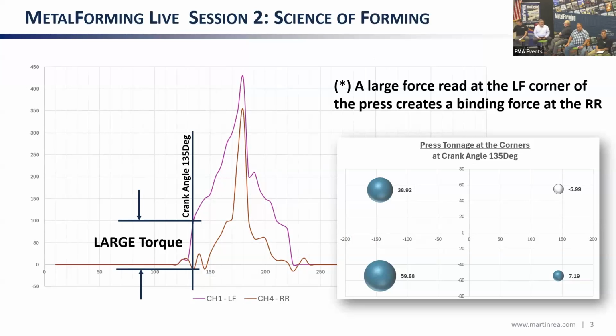Because of the signal we're getting from the right rear, we know that the press is sticking. The signal shows that while we're applying tremendous force in 3 of the corners, it actually goes negative in the right rear. The white dot shows a negative force. So even though you have a very high-tech, high-strength piece of equipment, you can see by some of the curves you get off the press that we're abusing that piece of equipment, and we don't want the maintenance problems that come with tools being out of line or presses being overloaded.